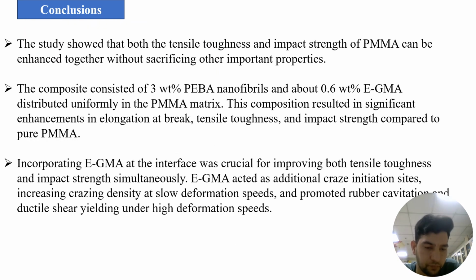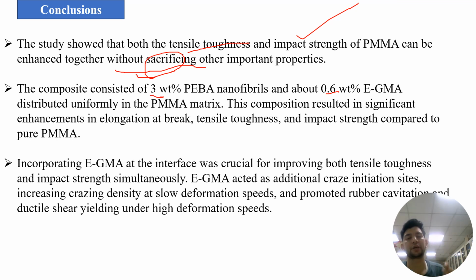Conclusion. The study in this paper showed that both the tensile toughness and impact strength of PMMA can be enhanced together without sacrificing other important properties. As I mentioned at the beginning, this paper is very interesting. Why? Because it does not sacrifice any other property, and the tensile toughness and impact strength are improved. The composite consists of 3% PEBA nanofibers and about 0.6% EGMA distributed uniformly in the PMMA matrix. This composition results in significant enhancement in elongation at break, tensile toughness and impact strength compared to pure PMMA.